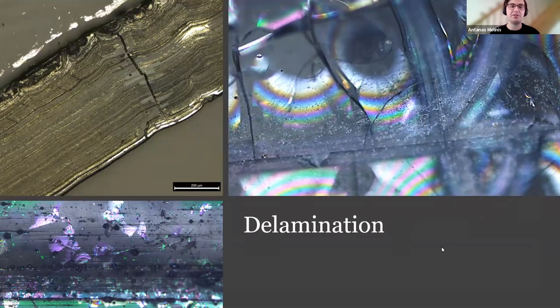And most of these hydrated crizzled layers are already poorly adherent to the parent glass, and it's mostly their surface tension that keeps them from separating. And crizzling further diminishes this effect, where the leach layer begins to gradually flake off. And this also permits ingress of moisture even deeper into the glass, creating a vicious cycle, which generally terminates in the complete disintegration of the piece if unattended.